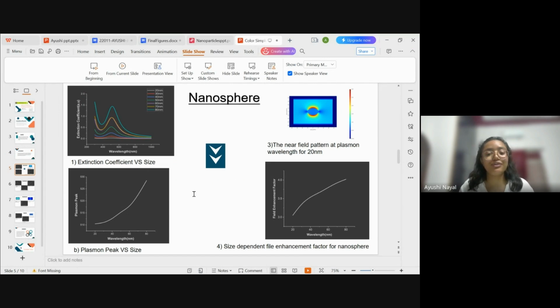So the first graph is for the nanosphere. As you can see, the first graph is between extinction coefficient versus the size for nanosphere. With the increase in extinction coefficient, the size of the nanoparticle also increases. This indicates that the larger particles are more efficient in scattering and absorbing the light. The B part, plasmon peak versus size, indicates that the value of plasmon peak is increasing with the increase in size of the nanosphere, as the peak shifts to longer wavelength, indicating tunability based on size. The third graph is for the field enhancement pattern at plasmon wavelength for 20 nanometer nanosphere.